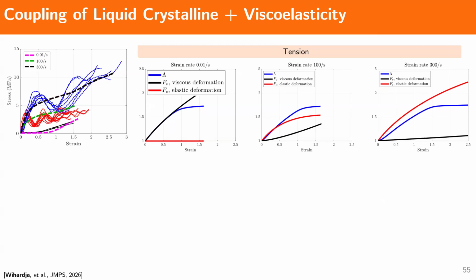Another important thing to note is that the soft behavior that you see under the quasi-static regime is very much suppressed when you test this material at high strain rate. Also, a disclaimer: this material has about 40% crosslink, so the behavior that you see is probably mostly dominated by the rubber behavior.